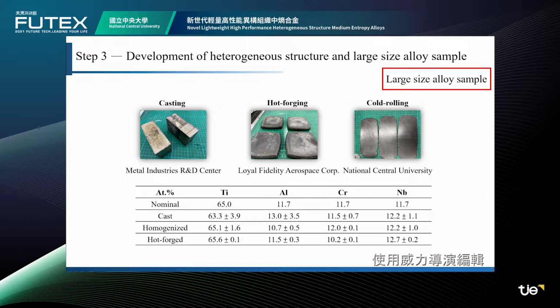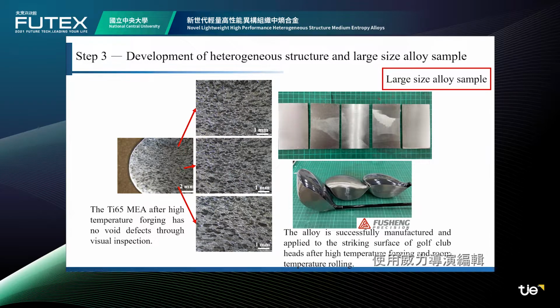Through EDS, we can see that the proportion of elements is close to the nominal composition after heat treatment or forging. And a stereo microscope was used to observe the surface morphology of the alloy after hot forging. You can see that there are no obvious defects on the surface after hot forging. Finally, we cooperated with Fusheng Industrial Company and successfully used the titanium 65 medium entropy alloys on the striking surface of golf club heads.